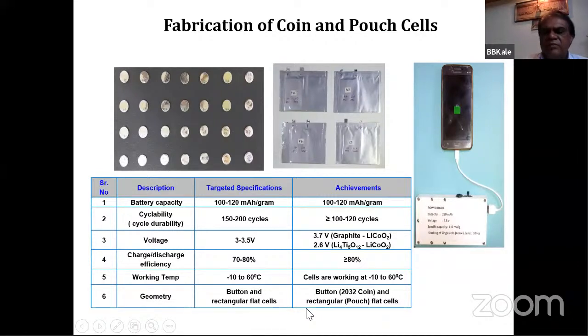Now we have a good facility for making pouch cells. So by stacking pouch cells, we can make batteries for mobiles. For each mobile, we have 24 stacked single cells, which means 24 cells together, connected in series for voltage and parallel for the capacity. If you have a good BMS, then we can design and stack these cells. A single cell is 120 milliampere hours per gram. Suppose you want to make a 2000 milliampere or 5000 milliampere battery, then this single cell has to be stacked up the required number of times.